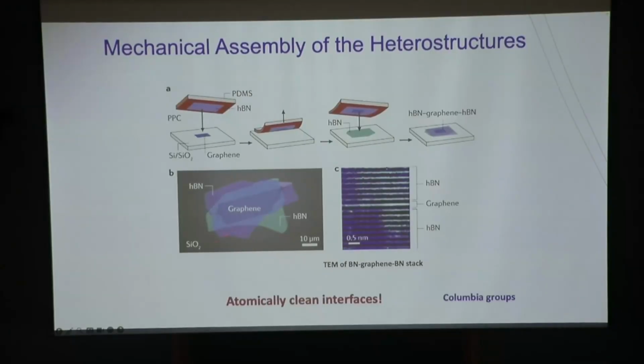So if you do TEM imaging of this heterostructure from the side view, you can see these individual layers of boron nitride, graphene, and boron nitride. They basically form perfect interfaces. So they actually form an atomically clean heterostructure, which is extremely important. If you want to study the fundamental behavior of electrons, you want the system to be very well defined and very clean. So this shows that this is indeed possible, and it led to a boom of a lot of researchers trying combinations of different heterostructures to explore different physics, like moiré heterostructures and so on and so forth.